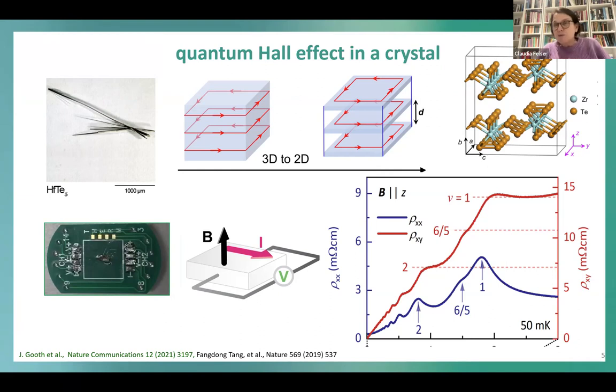You know, we missed several Nobel Prizes, Christina, because you didn't measure simply the right material. But you see, it even appears in this material. And why does it appear in the three-dimensional crystal? You can think about this two-dimensional material simply as a stacking of two-dimensional electron gases, which they made artificially in the work of Klaus von Klitzing by taking normal semiconductors and adjusting them. So these simple single crystals have it naturally, since you have a truly two-dimensional structure. So I think it's amazing. And this shows how strongly even this first invention is related to simple materials, which we have nowadays very often in the lab. And everybody knows hafnium telluride is not so difficult to make.